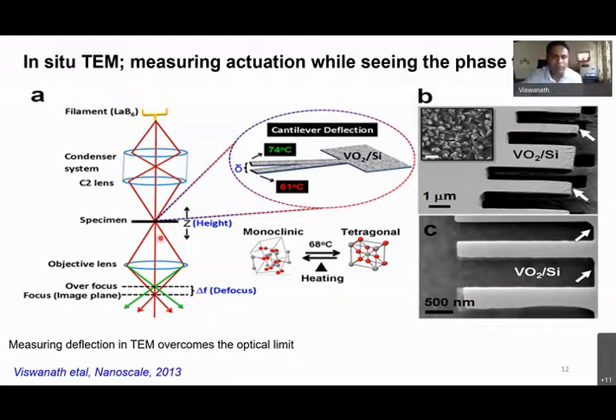Of course, many of you are most familiar with the transmission electron microscope and the ray diagram. All I'm going to do is only one thing. Instead of having a static specimen, I'm going to put my cantilever, which can deflect during the phase transformation. So the height will not be exactly the same. During the phase transformation, the sample can go up or down, according to whether I'm doing heating or cooling.